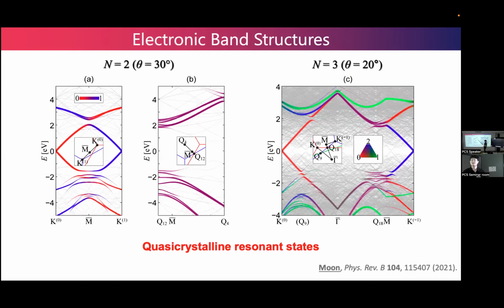And here I plot the band structure by keeping T0 at some value, at theta equals 20 degrees. Clearly, there are band features which deviate from the monolayer band structure. It reminds us of the quasicrystalline resonant state at a 30 degree rotation angle. But interestingly, this feature at what I call the Q18 point is different from the feature at this point, which means that there may be more than one quasicrystalline resonant state.